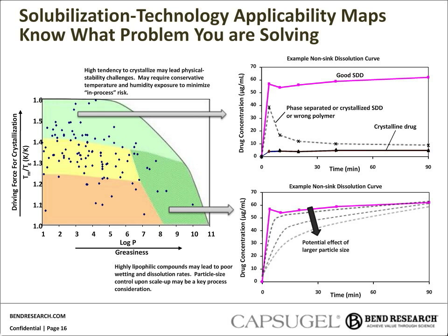The rate of precipitation is directly tied to the dissolution rate and the concentration of a precipitation inhibiting polymer. So with a good SDD, we see a rapid dissolution rate and sustainment of that concentration. If we have a drug that doesn't have the right polymer with it or too high of a loading, we will see this spike and crash phenomenon that will leave us with concentrations by 90 minutes in the biorelevant regime that are similar to crystalline drug.